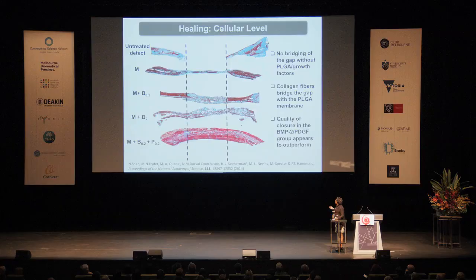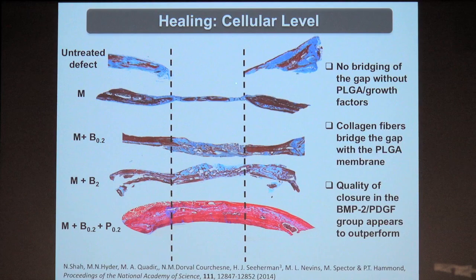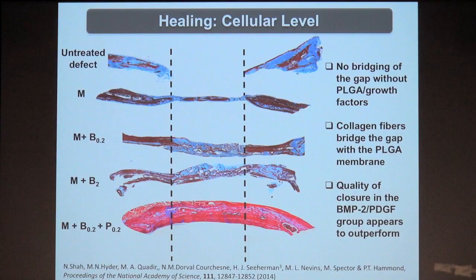Here you can see the margins. This is actually the bone that was originally in place. And here we see the hole. So this is a cross-section of the untreated defect. If we just put the membrane with no nanolayers on top in place, we get this kind of flexible collagen membrane. It's kind of a scruffy scab-like material, but it has no bone present and therefore is not mechanically appropriate.